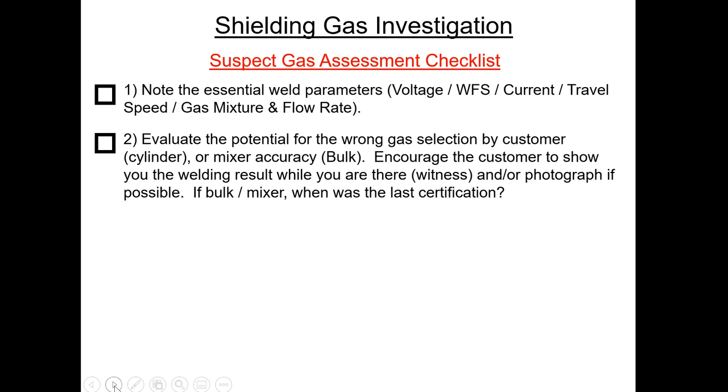Now, most of the time we're dealing with bulk gas, but let's remember one thing when we're talking about our regular gas metal process where we use argon and CO2. Here's an important point for you. If it was all argon or if it was all CO2, either one, you still would not get porosity. It wouldn't be the greatest weld, and there's lots of companies that run straight CO2 all the time.